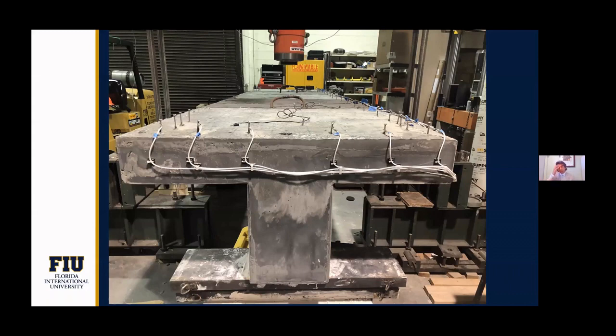Now, for those of you who are worried about the long-term performance, I think there was one question that asked. We have a faculty, Dr. King's Law, that is doing lots of corrosion study with this material. I can tell you that the long-term performance of this material is excellent. The reason for that is that this material chokes the system, doesn't let the oxygen and the water exist at the same time. The so-called corrosion people are really sensitive about this halo effect. There is no halo effect when you repair an element using this material. So the long-term performance, we've done work in this area, other people have done work in this area, is excellent.